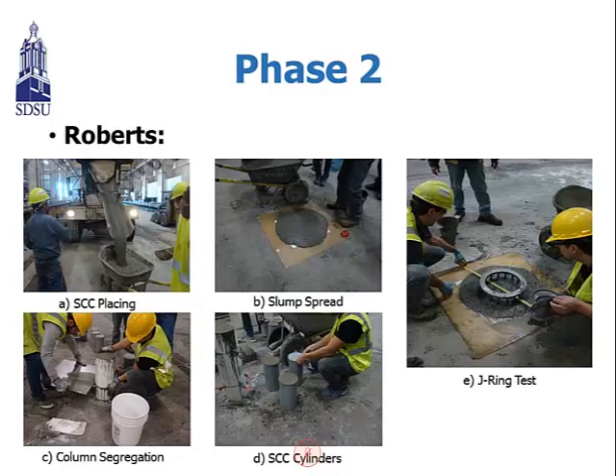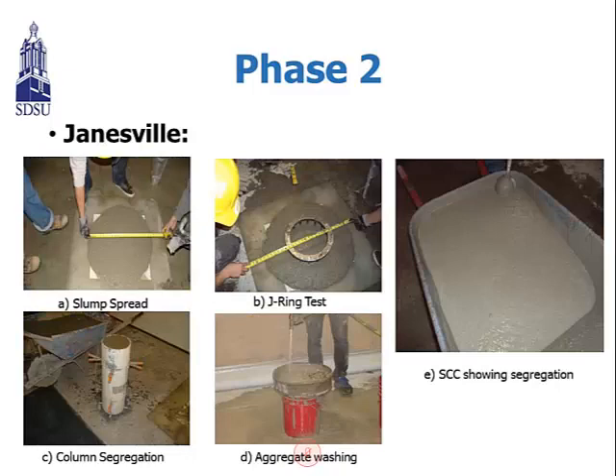So here's a picture for the testing and the casting of the creep and the shrinkage specimens. First we placed the SCC and we did slump flow, and also we conducted the column segregation again. We did mixtures 1, 2, 4, 6, 9, and also we conducted the J-ring test. Here's the picture for the J-ring and slump flow and the column segregation and the aggregate.